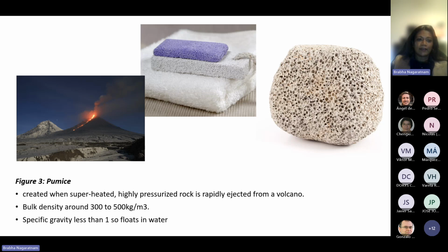If you look at the diagram of a volcano that I have, you can see two types of area. One is very dark, and one is probably where the lava has gone through. It's lighter. The aggregates are mostly whitish with a lot of holes, what we call vesicles. The bulk density of this type of aggregate is around 300 to 500 kilograms per cubic meter. To compare that with normal weight aggregate, which is around 1,500 to 2,000 kilograms per cubic meter, this is almost one third the weight of normal weight aggregate.